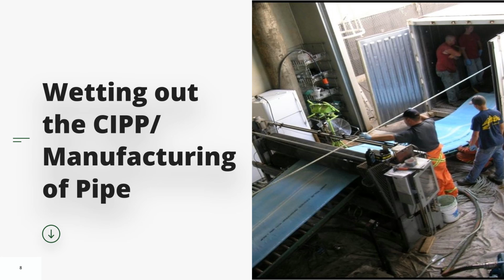That roller, because you know the strength of the resin that you're introducing, you know the thickness of the felt. What you're doing with that roller is you're setting the final thickness of the pipe. So if the design comes back and says you need a 25 millimeter pipe, you would set those rollers at say 53, 55 millimeters apart, which gives you your double 25 by 2 plus 2 or 3 millimeters for safety.